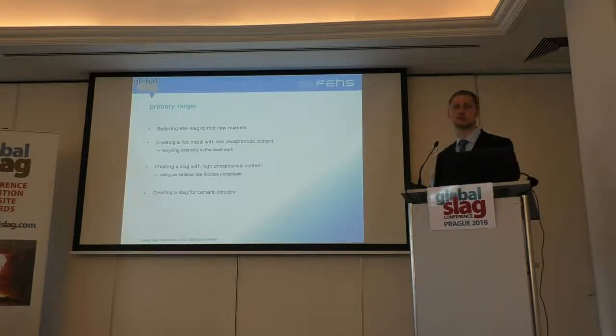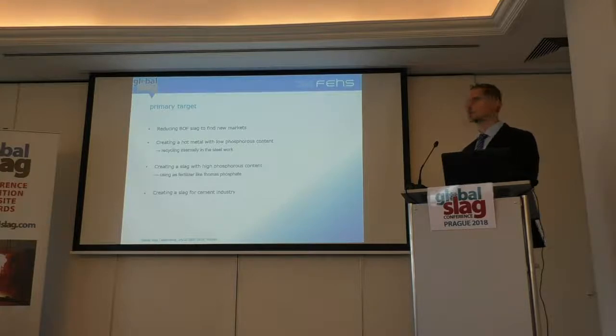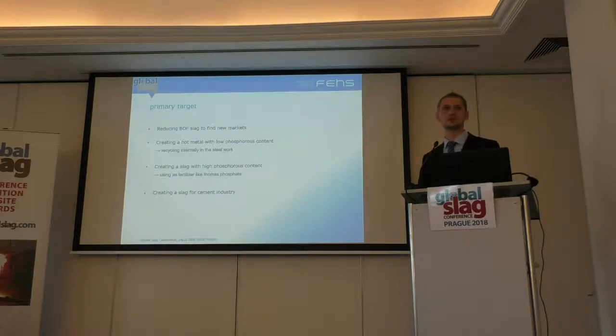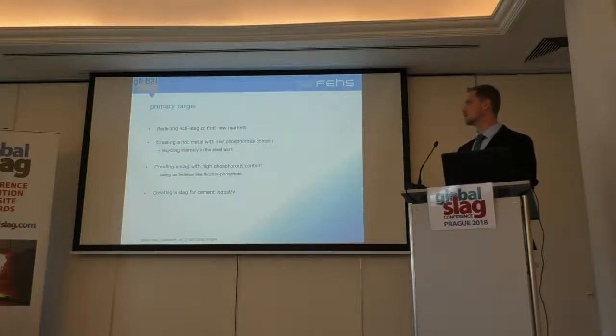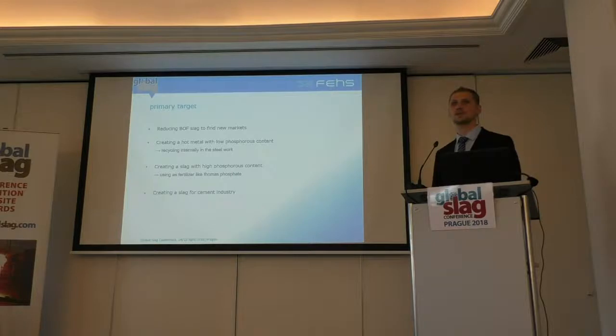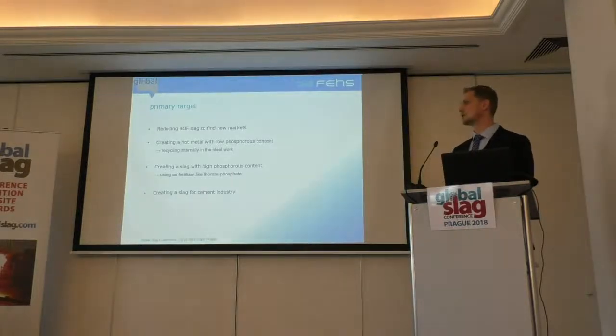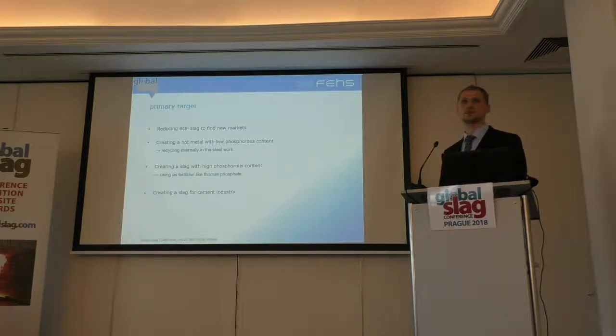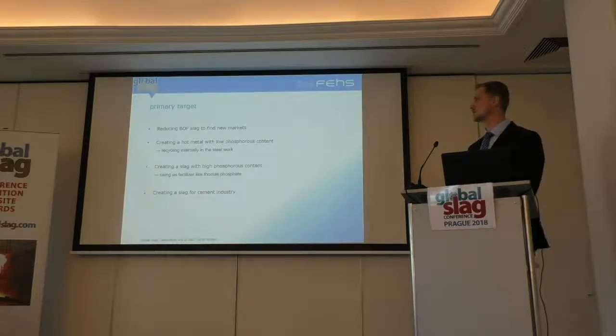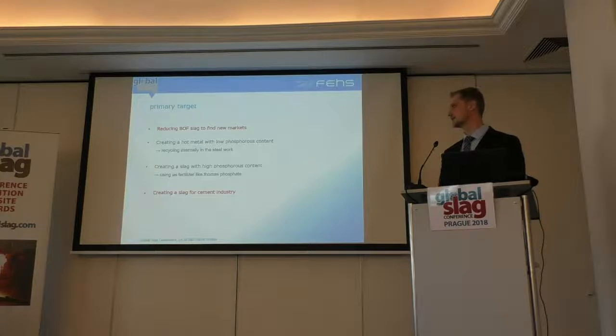We heard yesterday in the presentation from ArcelorMittal that especially the phosphorus is a limiting factor to recover BOF slag in the blast furnace or to the sinter plant. Our idea was, okay, when we get a high phosphorus containing metal, how can we reduce the phosphorus content and create a slag with high phosphorus, perhaps to use it as a fertilizer like the Thomas phosphate, and to create a slag for the cement industry. So today my presentation will be about these 2 points, the reducing of BOF slag and the creating of a material for the cement industry.